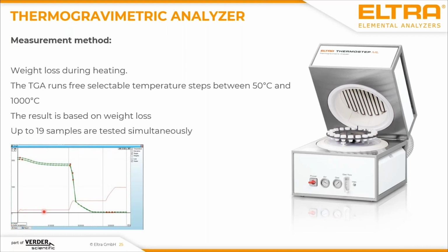You see it here in this graph. Here you have the temperature steps, 100 degrees, 550, and 1000 degrees. And here you see the loss on ignition, the loss on heating up your sample. So the first step is moisture. The second step here is then the TOC content, and then the last step is here. When we go to 1000 degrees, we see CO2 coming out of the samples. And these 19 samples are tested simultaneously, which means you don't need a muffle furnace or something like this. So everything you do in your thermogravimetric analyzer. And with this analyzer, you can automatically determine the LOI, the loss on ignition, of up to 19 samples without any attendance from outside.